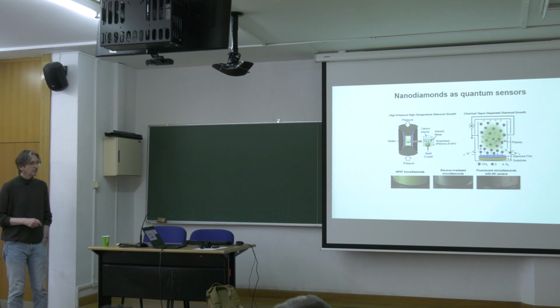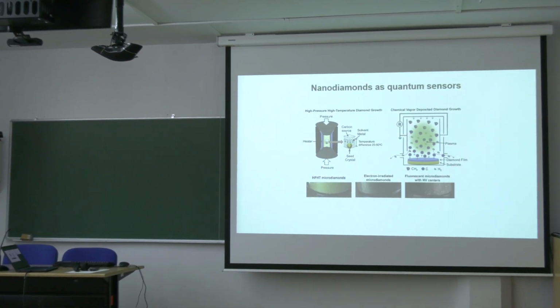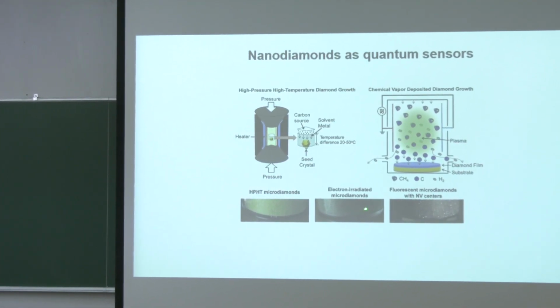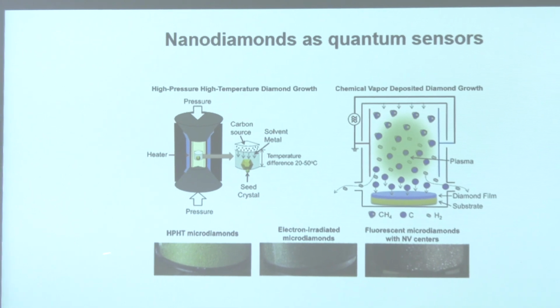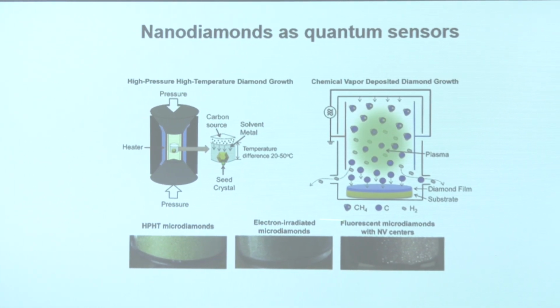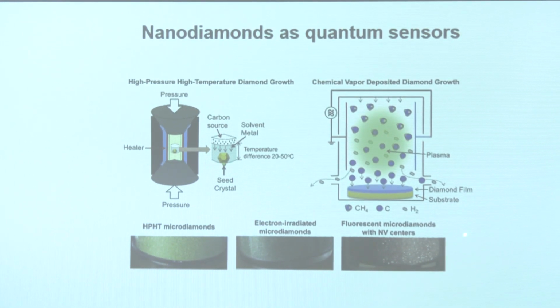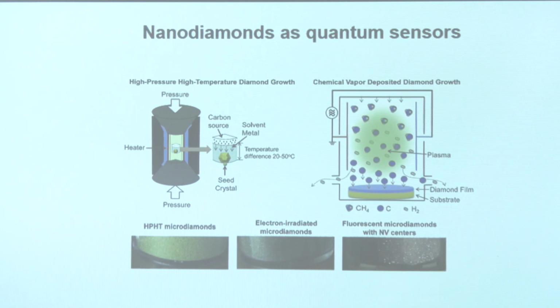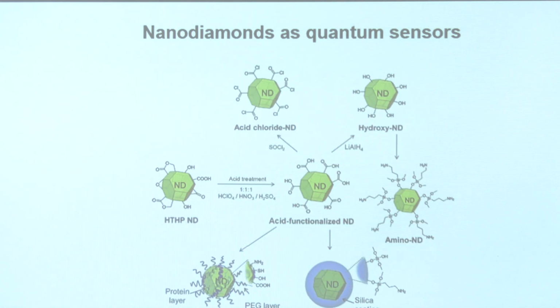Here I show you some examples of large-scale diamond powders generated by this high pressure, high temperature technique. You see the different colors. Actually, these colors come from different doping. This color comes from nitrogen presence. This is after irradiation with electrons. The green color comes from vacancies. And if you anneal this diamond, you get the pink color you've seen before for large diamonds. This is the color of NV centers. So those diamonds carry these spin qubits, and now can be introduced inside of a biological environment.